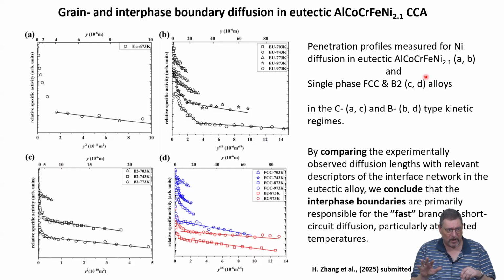But this was not known a priori ahead of time, right? Because nobody has measured interface diffusivity so far. And we then can conclude that interface boundaries are showing much faster mass transport along the boundary plane as compared to grain boundary diffusion. So it means one has to really take this into account if you think of interconnects. Whenever you bring two different materials together, not only for high entropy systems, they might be just a convenient model system. And then we basically have to worry about fast diffusional transport along this boundary plane.